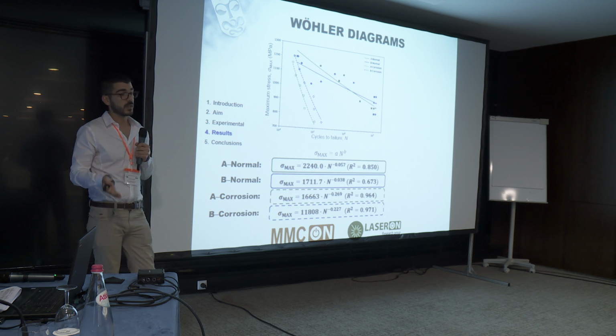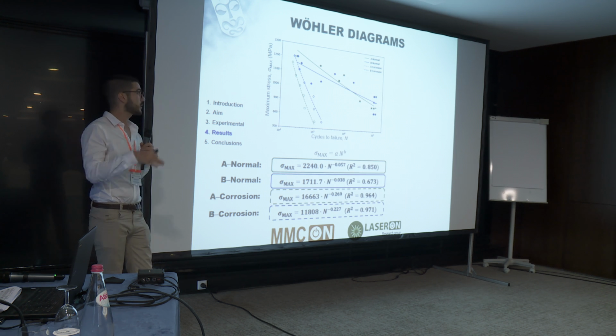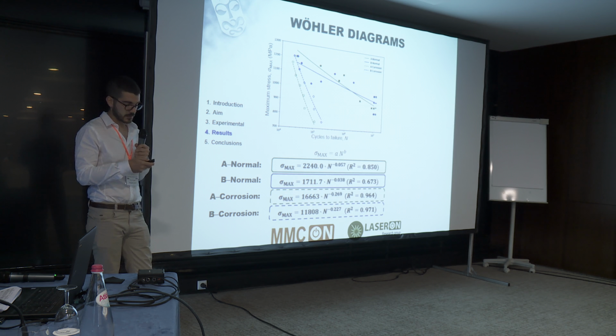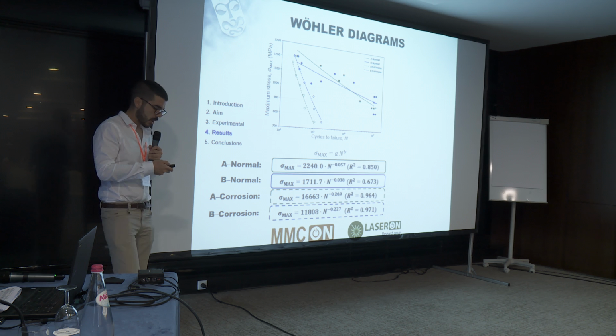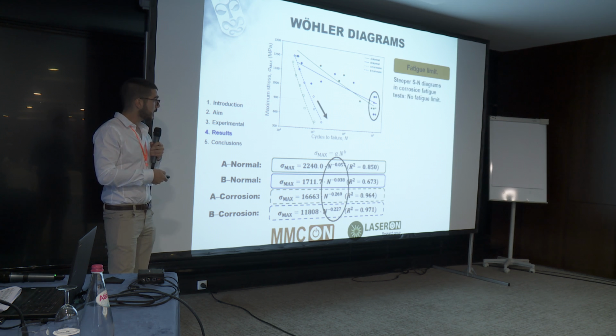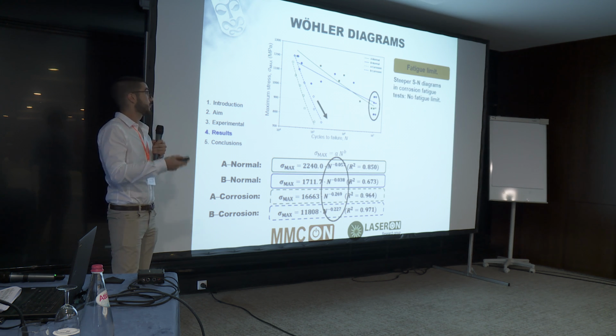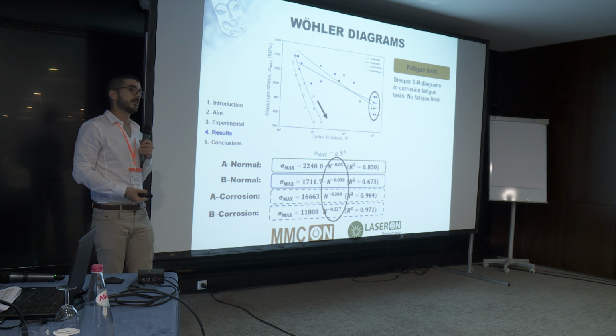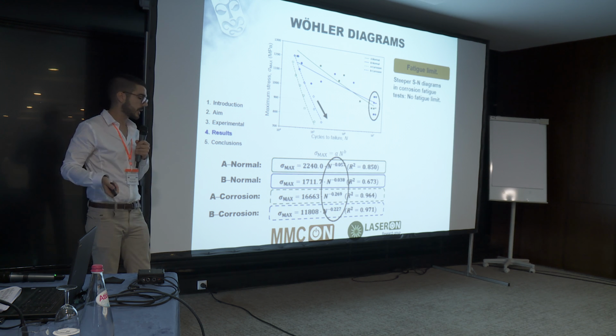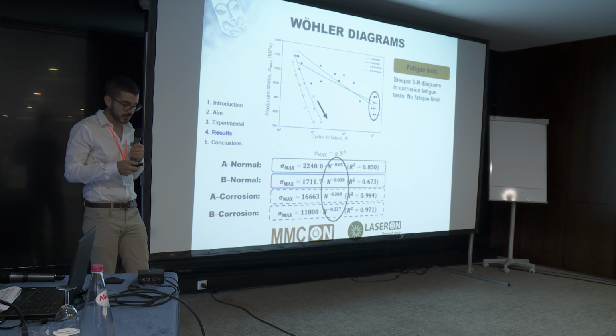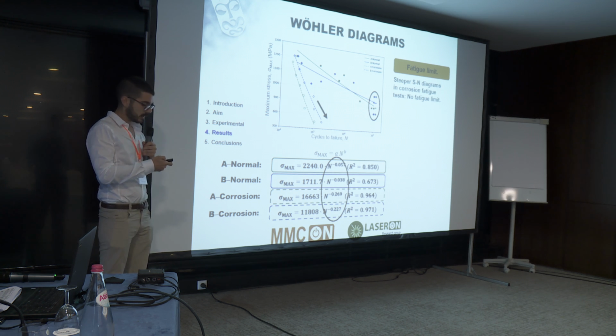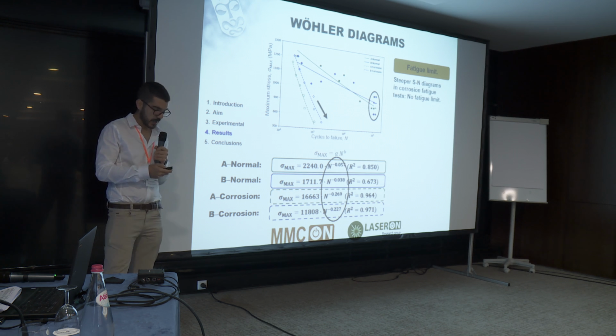Then, through regression analysis, we got fitting curves for each material and test condition, which are presented here. What we observed, of course, is that for corrosion fatigue tests the slopes are steeper and there's no fatigue limit. We can also see it in the exponents of fatigue strength here.